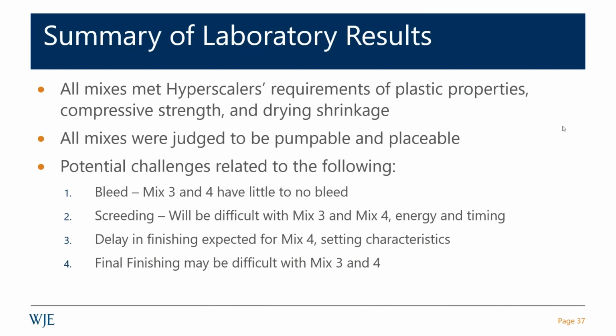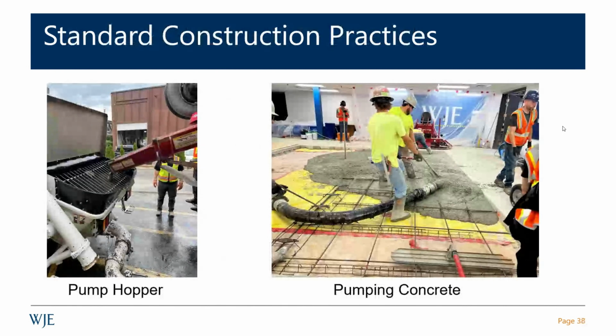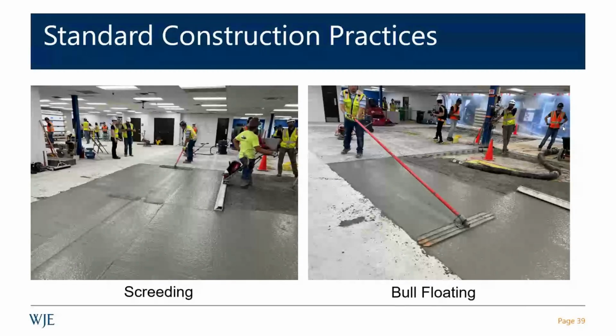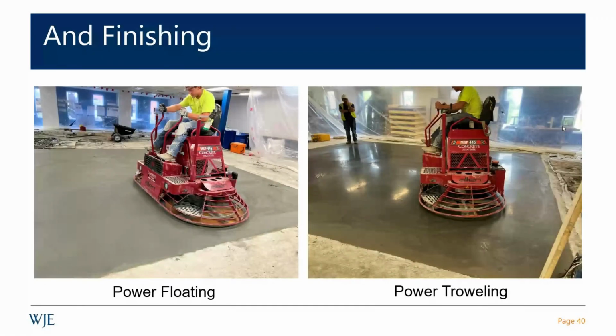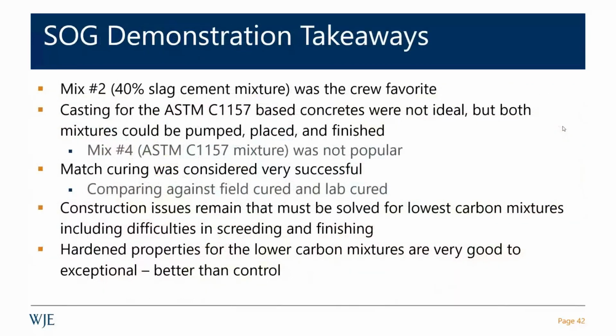But again, standard procedure. We actually put this into one of our warehouse buildings where we tore out the floor and built test sections, traditional finishing, hard troweling, floating troweling, and whatever. The takeaway of this was that, again, the 40% slag mix was absolutely the favorite. It performed exceptionally well. The hardened properties have been great. The abrasion resistance is high. There was absolutely no downside that was observed with that slag mix. And so that was really a big takeaway.